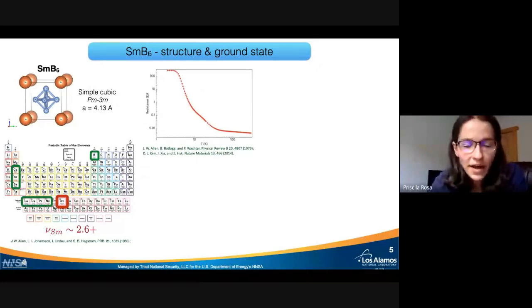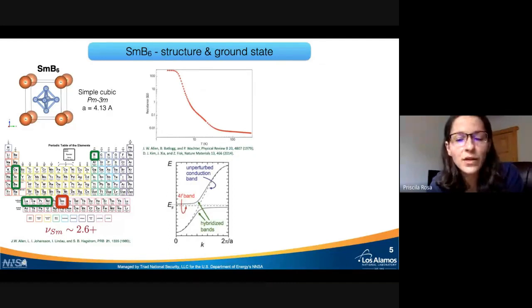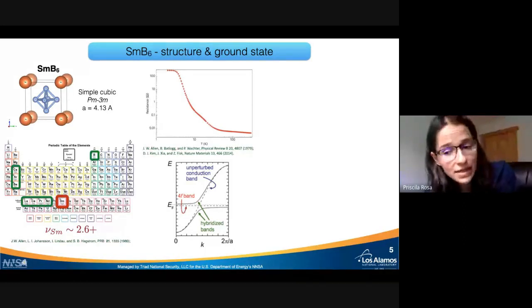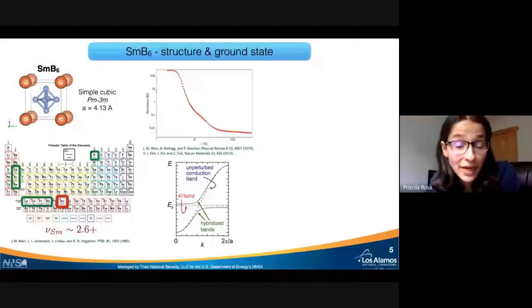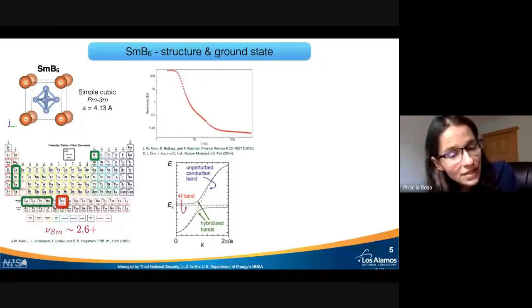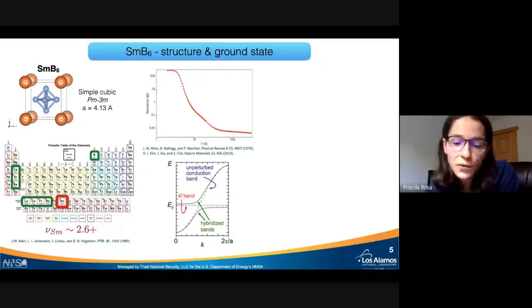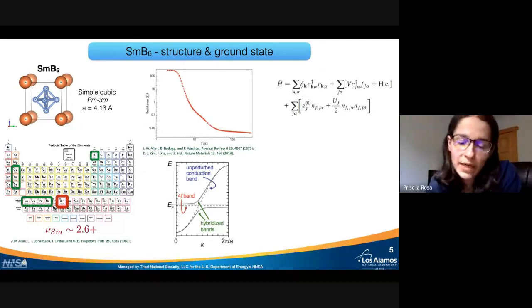And actually, there's a very nice and beautiful way of understanding this. And that's by looking at the hybridization between the F band and the conduction electron band. So below a certain characteristic temperature called the Kondo scale temperature, these two start to interact, and there is a gap that opens. If the Fermi level lies within this gap, the material will be an insulator. And this can be very nicely described by the so-called periodic Anderson model.